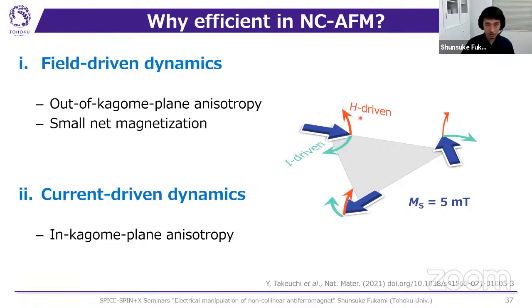So for the field-driven case, the moment in each sublattice should rotate out of the Kagome plane. So that out-of-Kagome-plane anisotropy determines the threshold field. But for the current-driven case, the in-Kagome-plane anisotropy basically determines the threshold current density. Because of the difference in the two anisotropies, the non-collinear antiferromagnetic systems show a much more efficient manipulation of the magnetic moment by current.